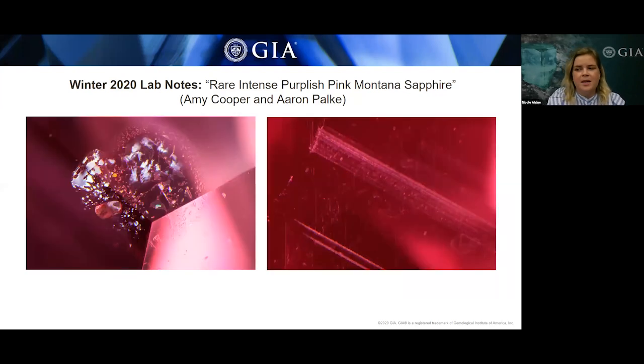Microscopic examination revealed intact crystals with decrepitation halos, seen in the photomicrograph on the left, and dense bands of exsolution silk interspersed with finer bands of silk, seen on the right, as well as reflective films and fluid films, all showing no signs that the sapphire was subjected to heat treatment. Advanced testing with ICP-MS was used to obtain the stone's trace element chemistry, which was consistent with Montana sapphires from the GIA Colored Stone Reference Collection.